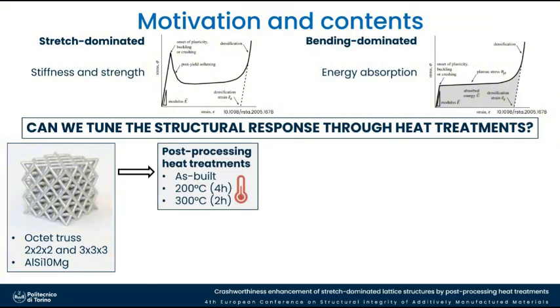Then we applied the post-processing heat treatments, one at 200 degrees, applied for 4 hours, and one at 300 degrees. And then we compared these results to the as-built conditions.